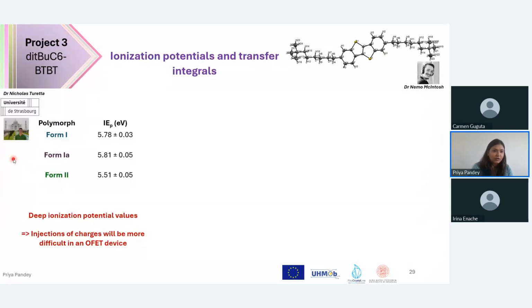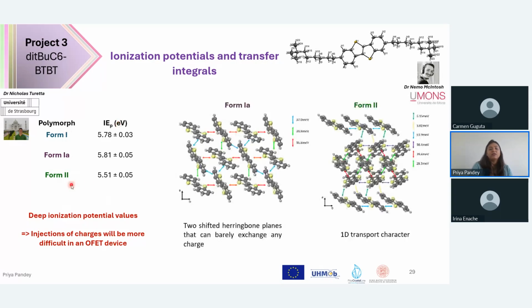To understand the reason, another project colleague of mine, Nicolas from University of Strasbourg, calculated the ionization potential values of different forms, and we could see why this molecule is not forming good OFETs: because of the deep ionization potential values, which means that the injection of charges will be much more difficult in an OFET device. And even the transfer integrals here are not the best, because they have 1D transport character, and in this case, they are made of two shifted herringbone planes that can barely exchange any charge.